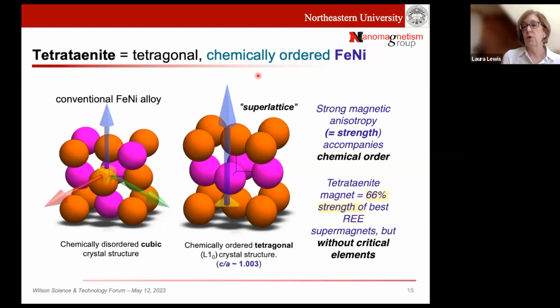Based on some of our work that we did on natural samples that were meteorites, if we are able to engineer tetrataenite perfectly, it can be 66% of the strength of the best rare earth magnets that are out there, but it does not contain any rare earths, no critical elements. And I will say that even at 66% of the strength of the best rare earth magnets, I still could not pull that off of my filing cabinet.